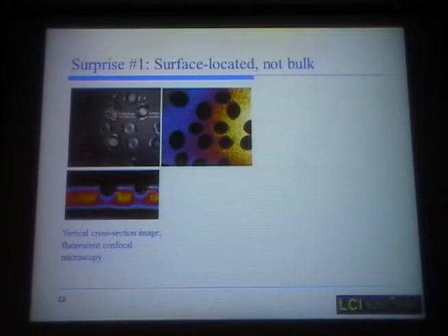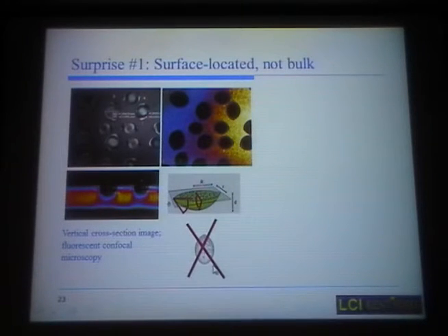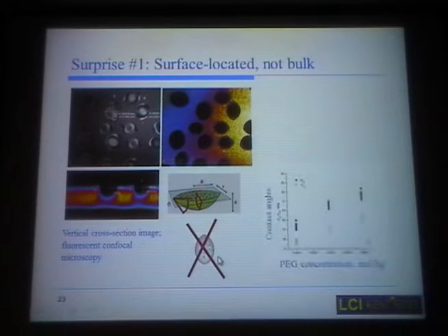by taking our three-dimensional microscope. Again, Ivan Smalyukh has a lot to do with this microscope that allows you to observe not only the in-plane structures but also the vertical cross-sections. And what you see is that the tactoids, these black regions, are not in the bulk as we are used to thinking most of the time. They represent droplets that are sitting on the top or bottom of the cell, attached to the substrate. So it's something like this, and nothing in common with this axisymmetric structure.